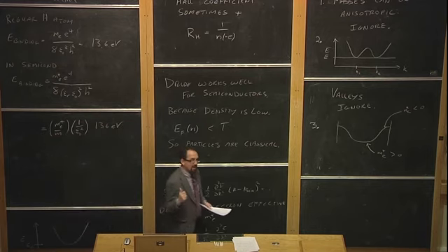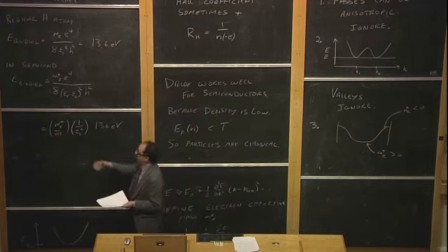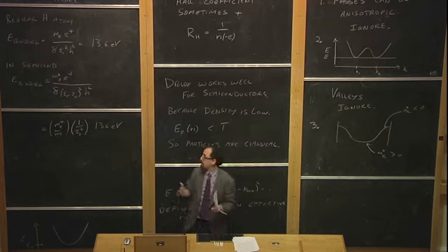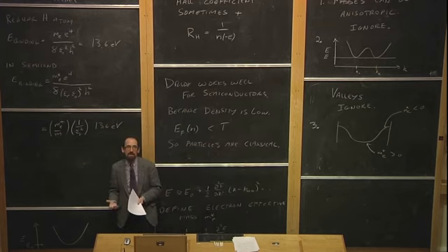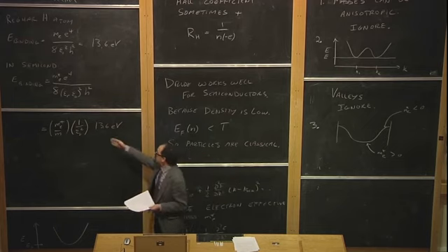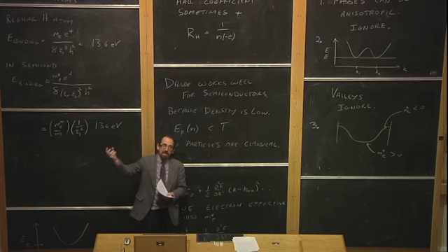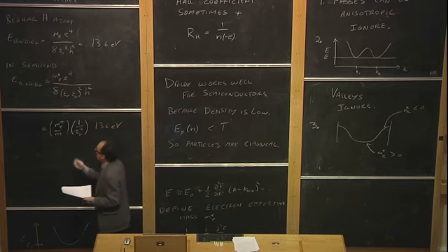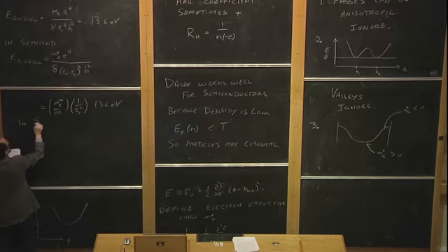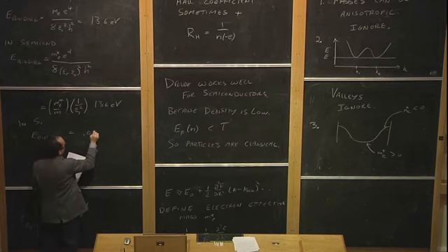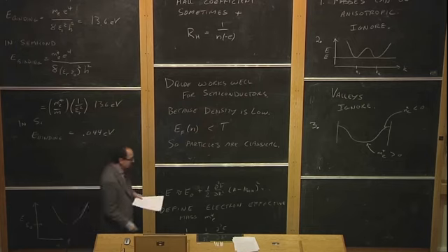Now, this expression can be a whole lot different from 13.6 eV, and generically it's going to be a lot smaller. Typically, effective masses of electrons in semiconductors can be 1/3 of the mass of an electron, or even 1/10 of the mass of an electron, or even smaller. The dielectric constant in semiconductors can be numbers like 10. So the actual binding energy of the electron to the proton in the semiconductor can be as much as a factor of 1,000 less than this. For example, in silicon, E binding of the electron back to its dopant nucleus is 0.044 electron volts, a much, much smaller number.